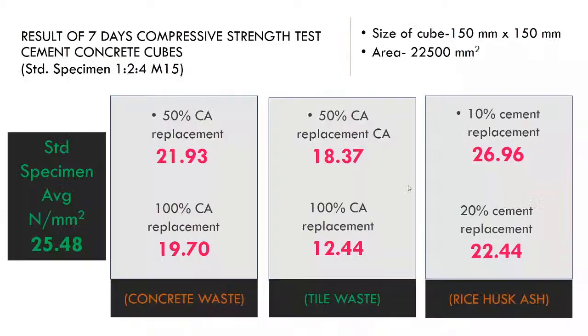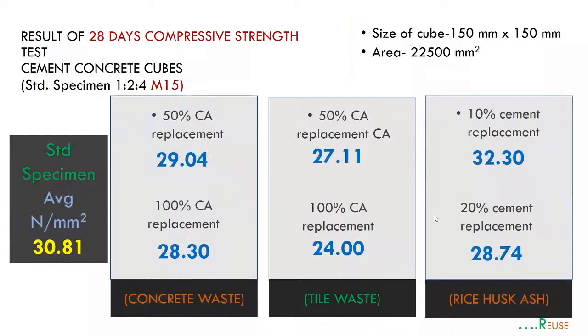One with the standard specimen, average specimen seen over here in the green font here. And see the table, 50% coarse aggregate replacement and 100% replacement with the concrete waste. Then the tile waste. See here, the tile waste did not give us much satisfactory result. Rather, it was very down. And now see, what about the 28-day compressive strength?